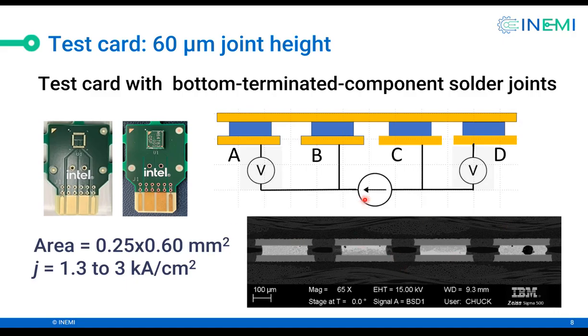So what we do is we have 4 solder joints, but only B and C are the ones we pump current through. So current flows like this. There is no current in A or D. A measures the voltage drop across B, and D helps to measure the voltage drop across solder joint C. And since we know the current, and if we know the voltage, we can measure the resistance of solder joints B and C. And here is just a cross-sectional view of the 4 solder joints.